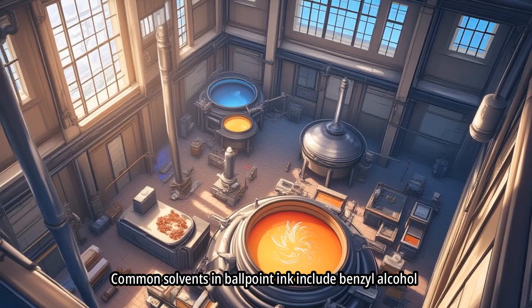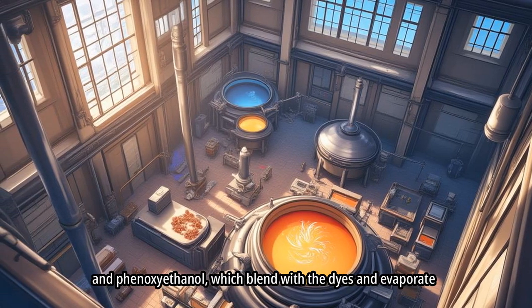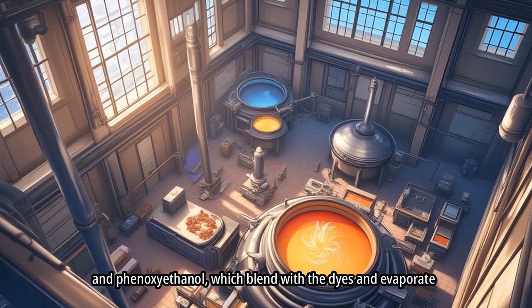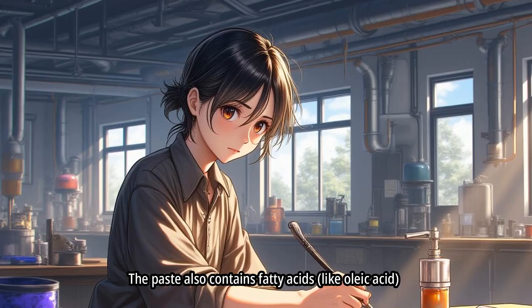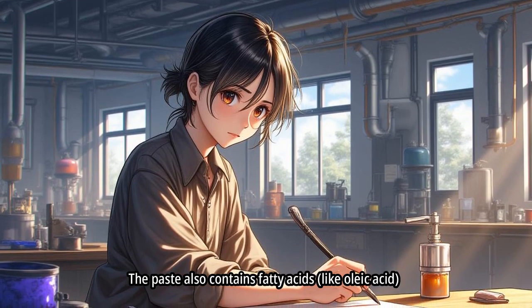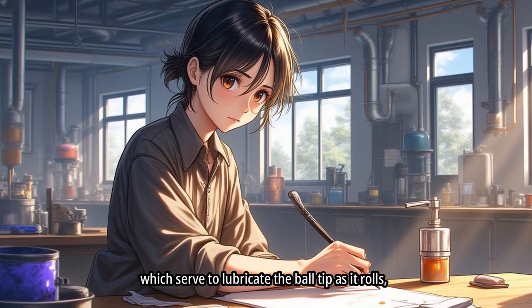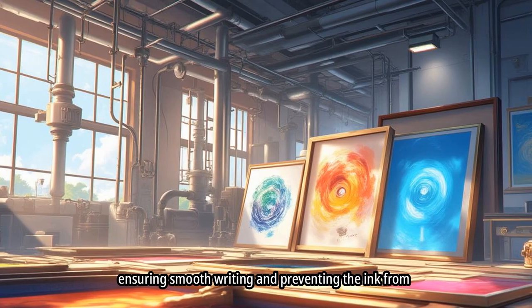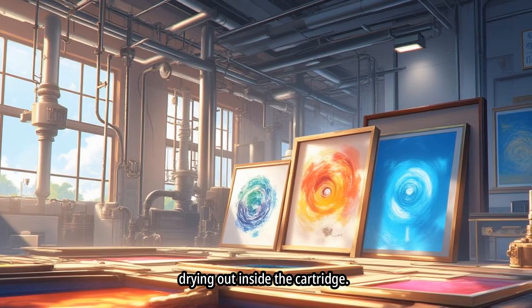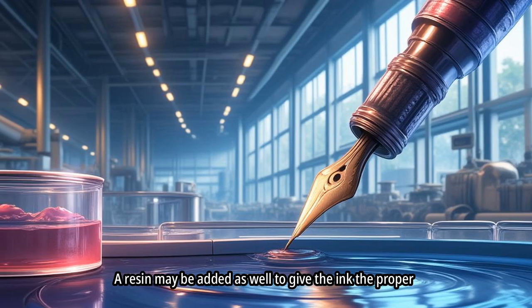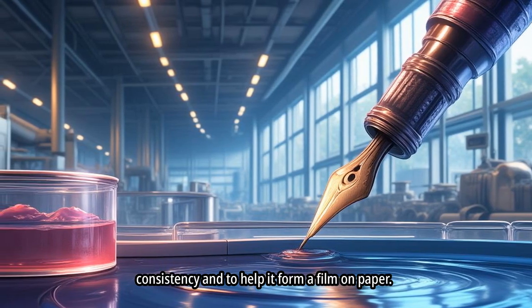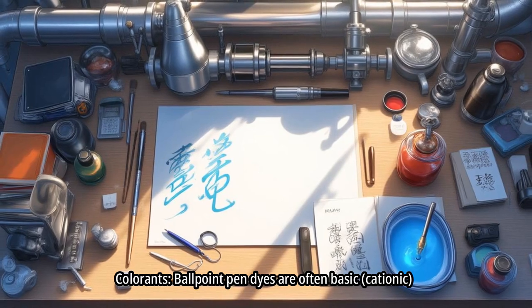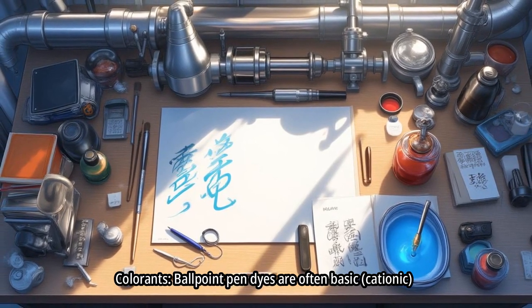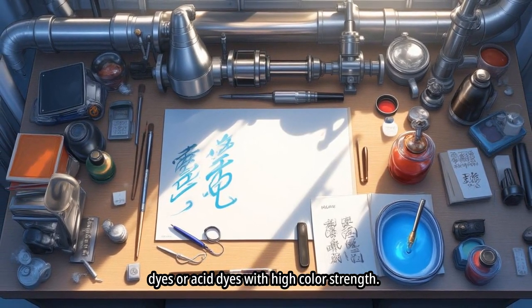Common solvents in ballpoint ink include benzyl alcohol and phenoxyethanol, which blend with the dyes and evaporate slowly. The paste also contains fatty acids, like oleic acid, which serve to lubricate the ball tip as it rolls, ensuring smooth writing and preventing the ink from drying out inside the cartridge. A resin may be added as well to give the ink the proper consistency and to help it form a film on paper. Colorants. Ballpoint pen dyes are often basic, cationic dyes or acid dyes with high color strength.